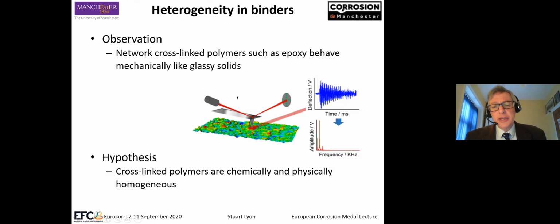So we were very lucky to get this atomic force microscope, which had a laser attached to it, which allowed us to do infrared analysis. Although the laser illumination was diffraction limited on the surface to several microns, the sensing area is dependent on the tip of the AFM, which is nanometers in scale. So we can do nanometer local analysis with AFM of our infrared spectroscopy.